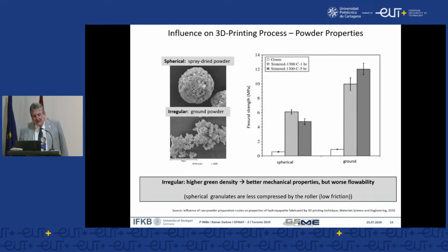So there are sometimes agglomerates. I will not go into so much detail with the ceramic technologies, but just to show you on the right hand side, if we have the spherical granulates, the green material has a very limited flexural strength in a reference sample. These tricalcium phosphates typically are sintered at a maximum temperature of 1300 degrees C, depending on the grain size, in the range between 1 hour and 5 hours, for example. There is a maximum, in this case for the 1 hour thermal treatment time, and we see a flexural strength of 6 megapascal, which is not so bad for a printed material.